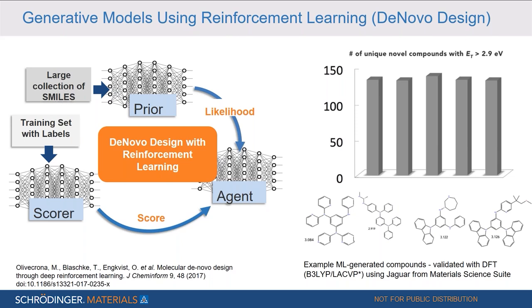Let's take a look at a practical example on the right-hand side. And here the target property was a triplet energy higher than 2.9 electron volt. And the training was done in pure organic space, so for TADF molecules. And the procedure was replicated 5 times. So each bar in the bar plot represents one run. And the top 150 molecules from each run were saved. And if you take a look at the structure, those are the number of unique novel compounds which have a triplet energy larger than 2.9 electron volt.